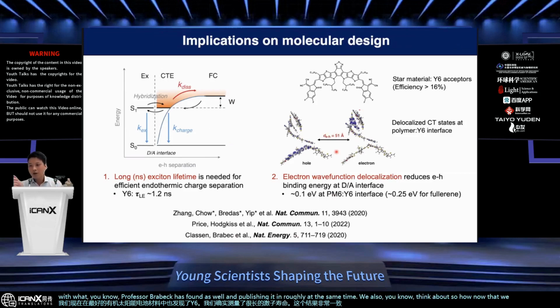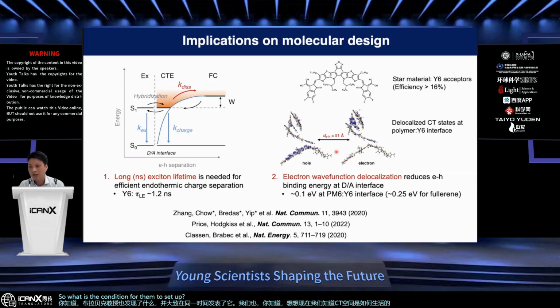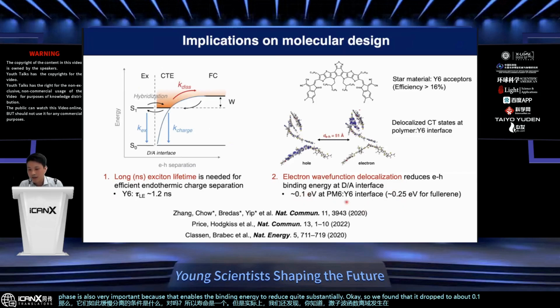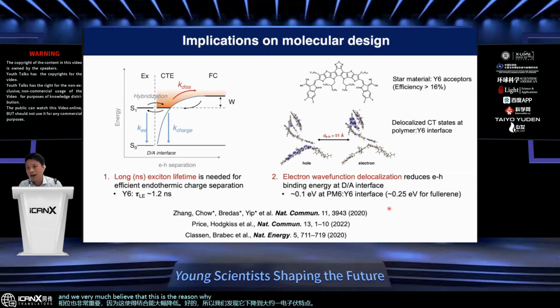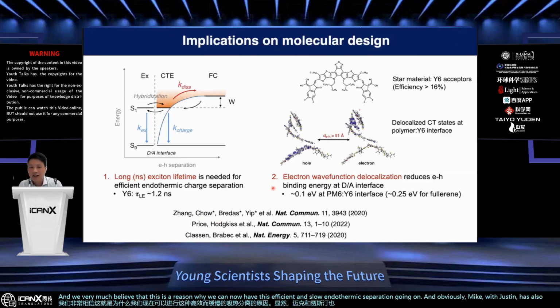Now that we know the CT states live for a long time, what is the condition for them to separate so slowly? Lifetime is one. But we also find that the exciton wave function delocalization at the interface is very important, because that enables the binding energy to reduce quite substantially. We found that it dropped to about 0.1 electron volts, and we very much believe that this is a reason why we can have this efficient and slow endothermic charge separation. And obviously, Mike and Justin have also done a lot of work on these materials. We can discuss more in the panel discussion.